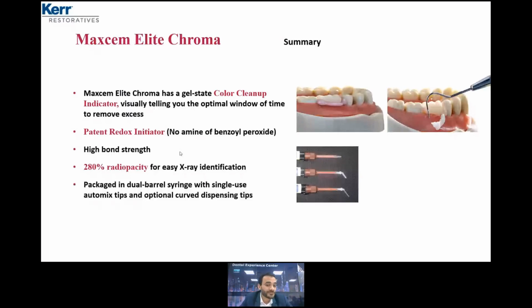It's a dual cure cement, yes, it's auto-mix, and for that we have specific and different tips. You have tips with a small opening, with a narrow opening, with a wide opening in order to attach for the intra-oral tips, or in case you need to use Maxcem Elite Chroma for cementation of metal post and fiber post, it is recommended to use intra-canal tips in order to be able to inject the